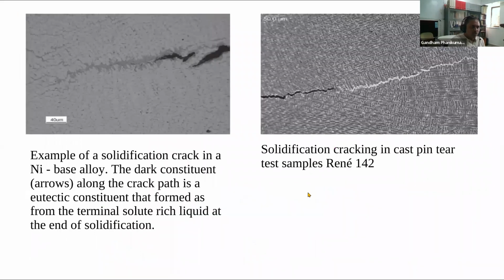So how do those cracks look? Solidification cracks can be quite serious, in the sense that the material has such a big crack that you simply cannot heal it and you can't use the component. The component has to be thrown away. Now, if you know the cost of printing a component, it can run from about $1,000 to $2,000 sometimes, depending upon the size. And if you have to throw it away because there's a big crack, that's quite sad. So we must understand this phenomenon carefully and avoid having that in our printing.